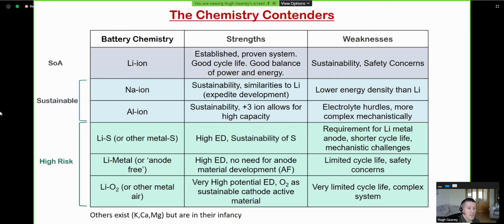Another high risk would be lithium metal, or also anode-free. Lithium metal is where you have a lithium metal anode and a conventional cathode material, which obviously gives you high energy density. In terms of anode-free, you actually don't have any lithium at the anode side, and the only lithium that you cycle is from the cathode. These have seen lots of development in the last maybe year or 18 months. One of the main issues with this is the limited cycle life. It's very difficult to work with the lithium metal anode, and I'll show a couple of the reasons why in a future slide.